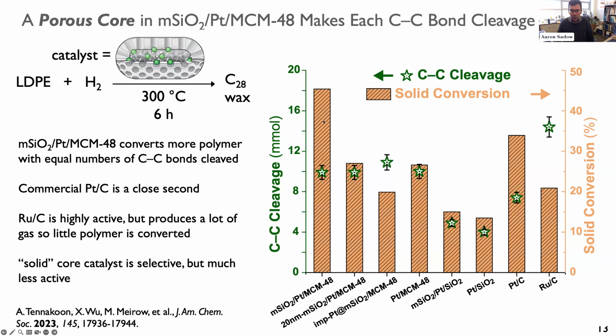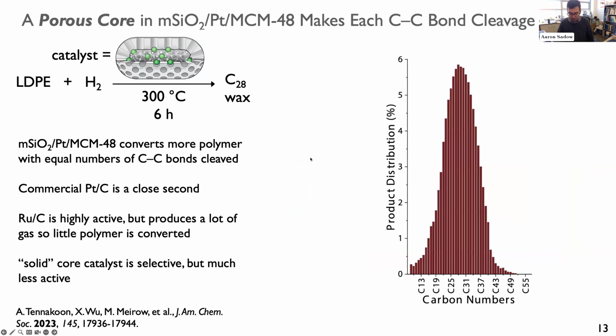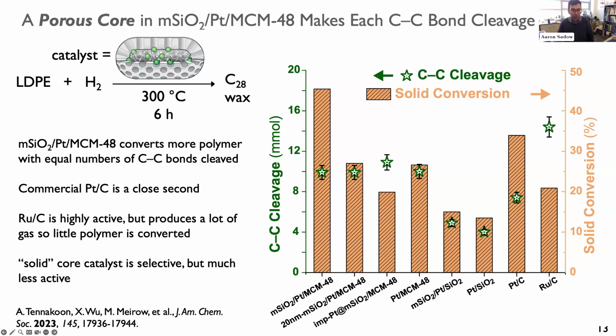So that's shown here. So the catalyst I'm describing and that we have as a cartoon here is shown here. The stars correspond to the C-C cleavage. So we're measuring the number of carbon-carbon bonds that are broken as we're doing the conversion. And then the bars represent how much of the polymer itself is consumed. So you can see that at, I think all the time, this is normalized by time. So this particular catalyst, this mesoporous core catalyst, is very effective at deconstructing the polymer to this Gaussian distribution.